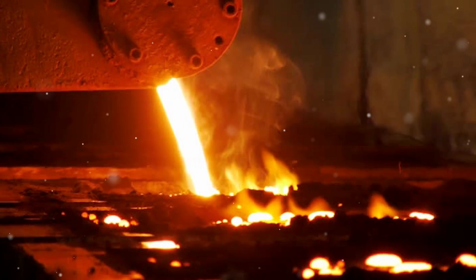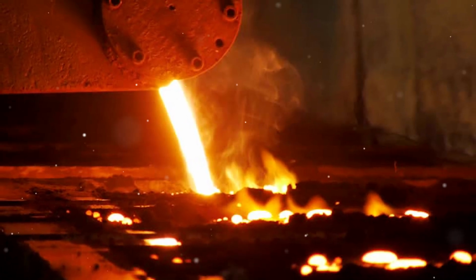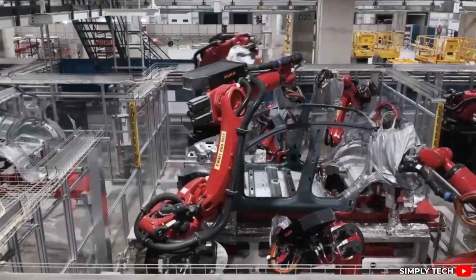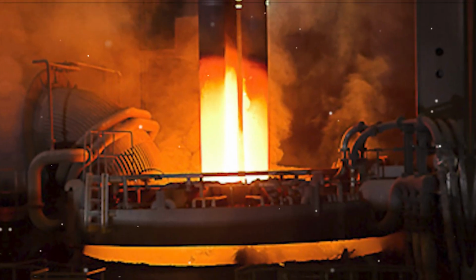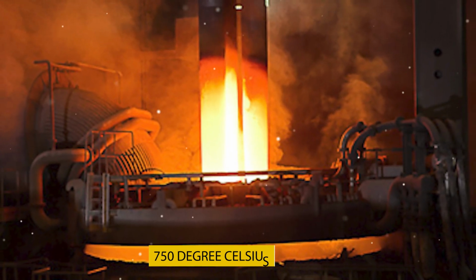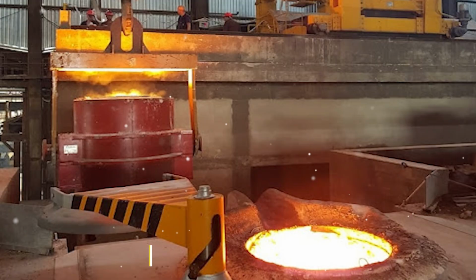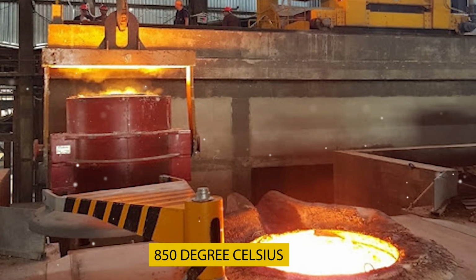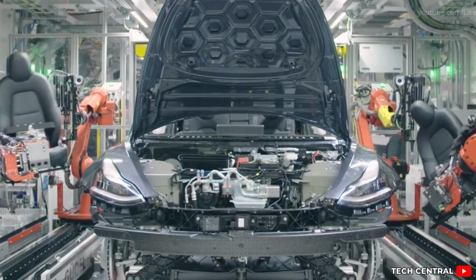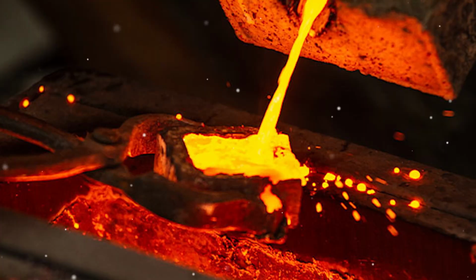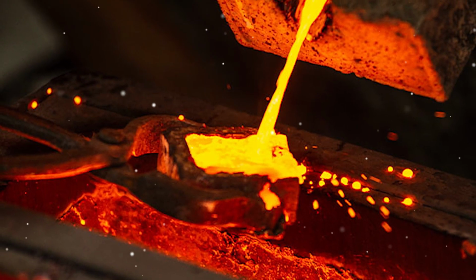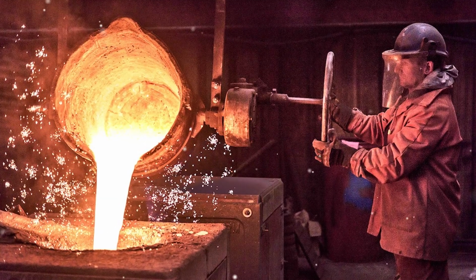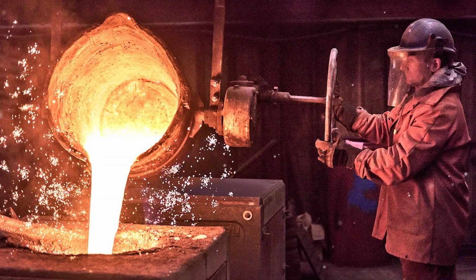Once liquefied, the aluminum is moved through heated pipelines to a second furnace, which operates on electricity and holds the metal at temperatures between 750 degrees Celsius and 850 degrees Celsius. This dual furnace system keeps things running smoothly. One melts, the other maintains, like a fiery tag team for uninterrupted metal flow.